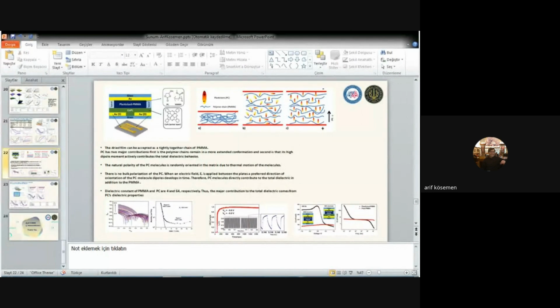Finally, we got high performance organic field effect transistors. We used high-K composite polymer gel dielectrics. In this study we again used propylene carbonate as plasticizer and polymethyl methacrylate as the polymer chain to get the matrix. And we added silicon dioxide nanoparticles to this gel-like structure to get more stable and higher mobility values. This approach gave our best mobility value, 4.66. This is our record value, and we got it with 50% silicon dioxide in the PMMA gel dielectric structure.